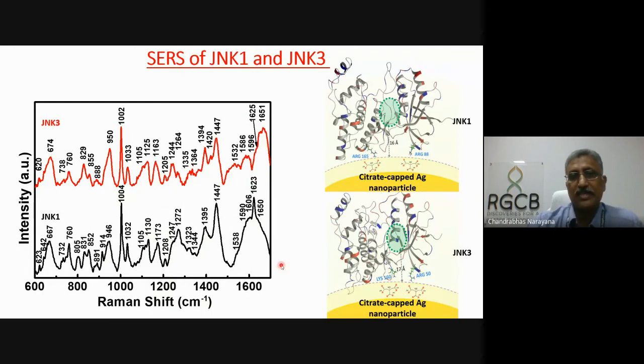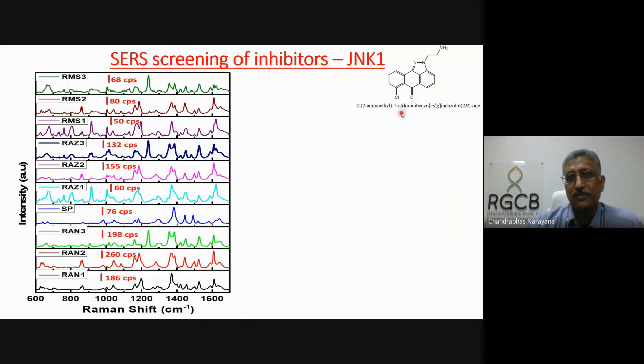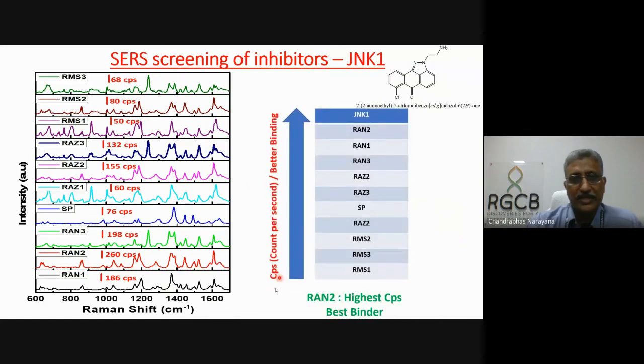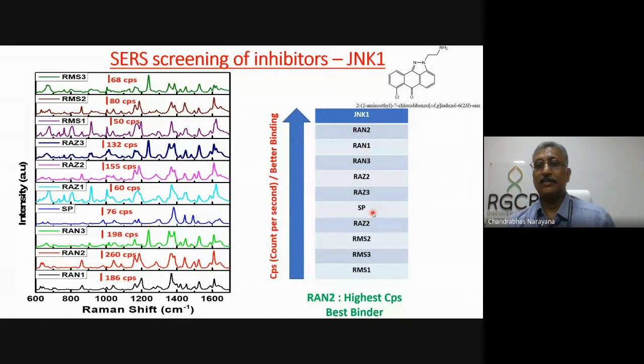So we know the spectra of the JNK. What we did is we put the inhibitors at different points, and we looked at the intensity of these. These are all normalized Raman spectra. You can see RAN2 has the highest intensity, which means RAN2 binds much more strongly to the system compared to even the SP, which is the original molecule. So based on this, I can actually tell which binds better. RAN2 is the molecule which binds best to JNK1. It is much better than even the initial molecule we started with. And this is the ranking of the different molecules, so you know which is the best molecule.